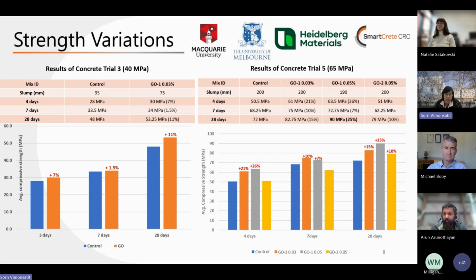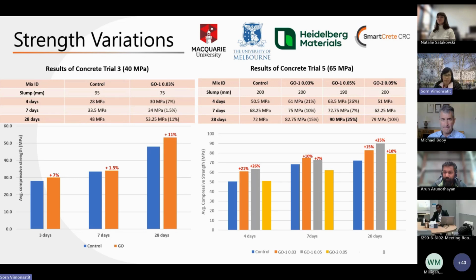So the remaining part, as Michael has already mentioned, the mixes we've done: there were 3 main commercial mixes with 3 different strength grades. With that, like what Michael said, the two key properties we checked are the slump retention and the compressive strength. Michael, correct me if I'm wrong, the compressive strength test was done at your facility. Yeah, and some of the durability tests were done at the University of Melbourne.